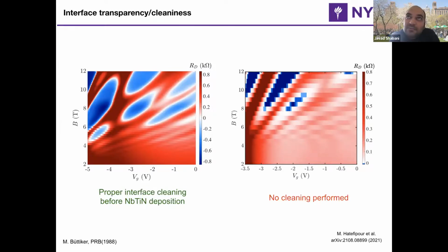And one thing that we can do is just not care about cleaning of the interface. So just expose the sample to air and then put it back into the sputtering chamber without doing the in situ cleaning and etching of aluminum and putting niobium titanium nitride. The sample measurement is on the right-hand side. The one that we were discussing is the left-hand side.